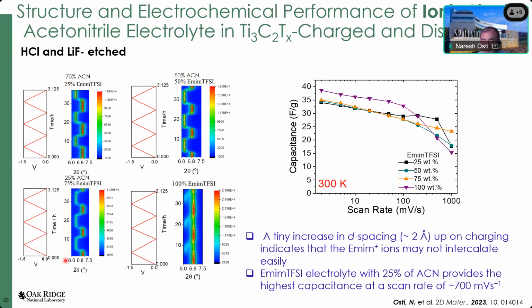But what we found from the XRD structural characterization is that there is no significant increase in the d-spacing once you add the organic solvent in the electrolyte system. We simply found just a 2 angstrom d-spacing increase once you charge the system. This 2 angstrom increase in the d-spacing is not enough to hold the bulky cation of the ionic liquid, which is somewhere around 8 angstrom in average diameter. It gives us an idea that maybe the ionic liquid is not in between the layers in this system as well.